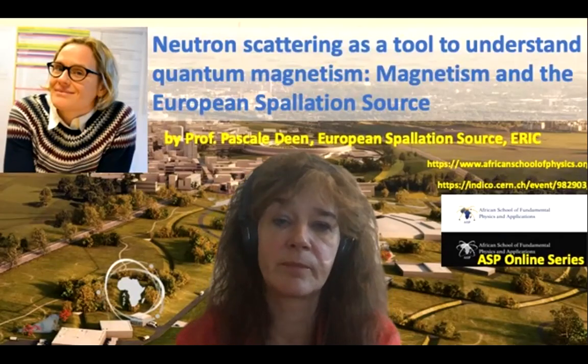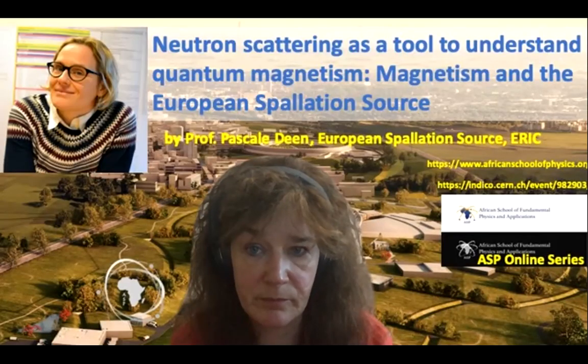Once you do an inelastic neutron scattering experiment, there are things you can do. It depends what you're looking at. For a spin liquid, we're still very far away from having any proper theoretical insight. But if you have a more simple classical system, multiferroic or something like that, then you are able to use the more generic tools that I showed. You can look at how far up your excitation spectrum goes. What is the lifetime of your spin state? Is your system gapped or not gapped? Do you have a gap, which means that you have some anisotropy in your system, and things like that. But these days you do not publish anything without theoretical comparison.